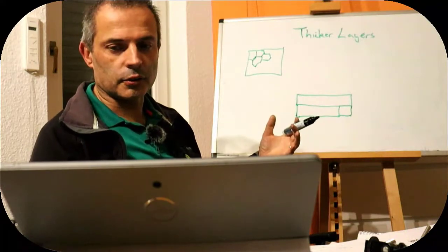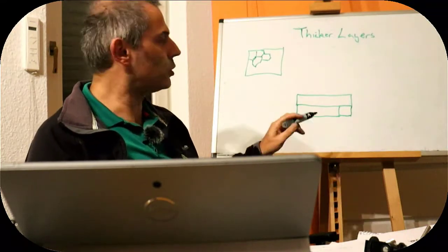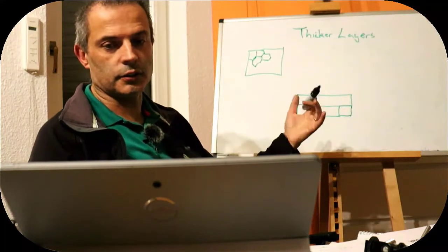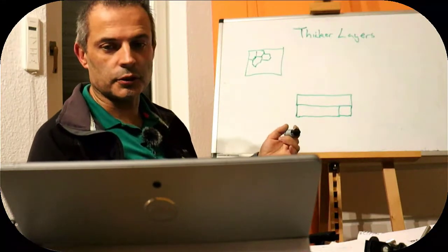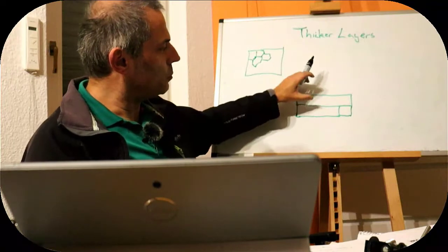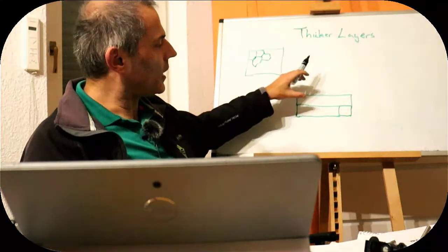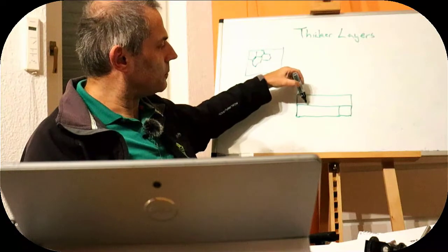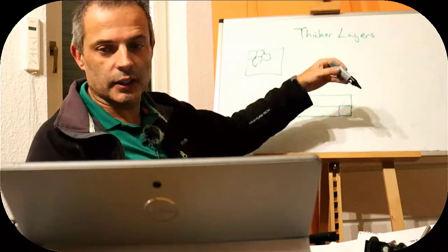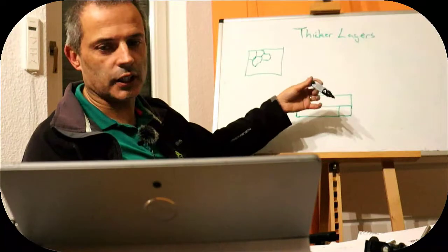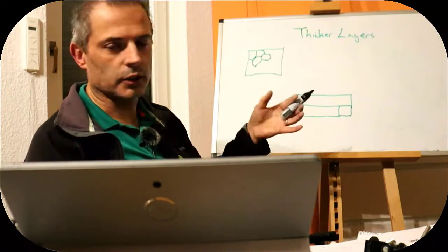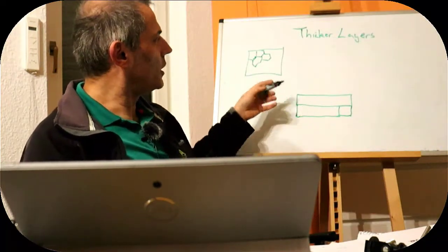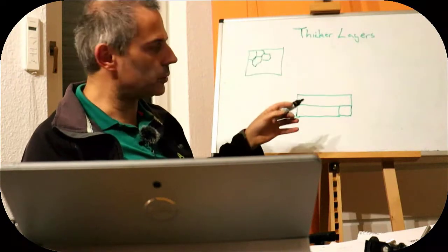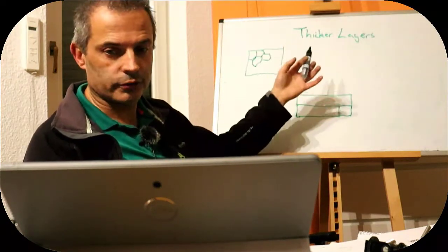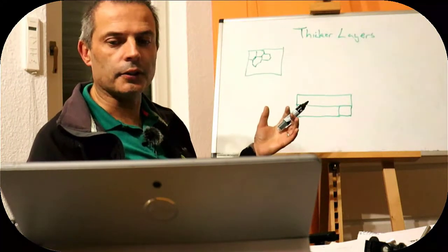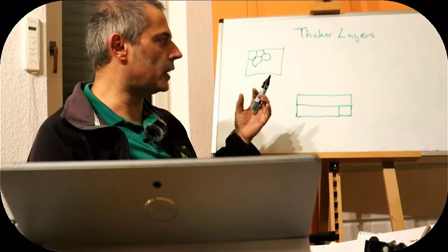In the case of compressive stress, we have exactly the same problem, that our interface is stressed from the interfacial stress. It's trying to bend away, and also the film will crack in some places. So then we will tend to get delamination in the same way, but with a slightly different shape, and we won't get these cracks with gaps in between. We'll tend to get bits flaking off. So we need to think of some way around that if we're going to generate a thicker film.